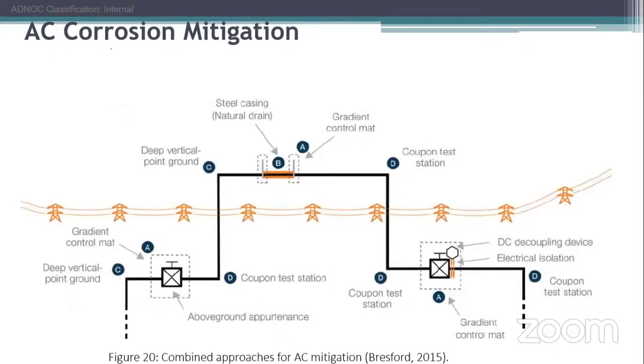So you understand, to protect our pipelines from this form of corrosion, we can ground our pipelines. We can use DC decoupling equipment. DC decoupling means it will prevent DC from grounding and allow only AC to ground. The DC comes from the cathodic protection, because if we just ground the entire pipeline, both the cathodic protection and the AC will all go to the ground. But we need our cathodic protection to protect the line.